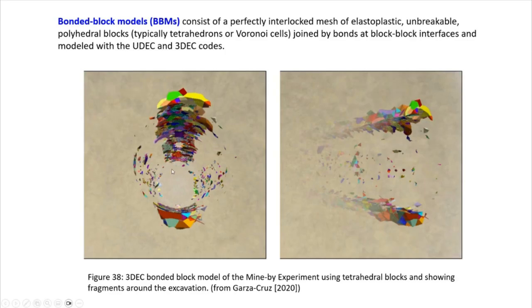And if you load a borehole or an opening like that, you're mostly squeezing it, so you get really high compression above and below, and it ends up causing this localized damage. Many people call this a notch. And so the only thing we're seeing in this model is the blocks that have completely broken free from all surrounding blocks. We call those fragments. So this yellow guy, all of its polyhedral interfaces have broken, okay? And this is just looking at it from the side. And so this has localized now into this damage above and below this notch. And there's also some tensile failure in the walls. This is quite realistic. This is matching the behavior of a certain thing called a mine by experiment. So that's a bonded block model in 3D.